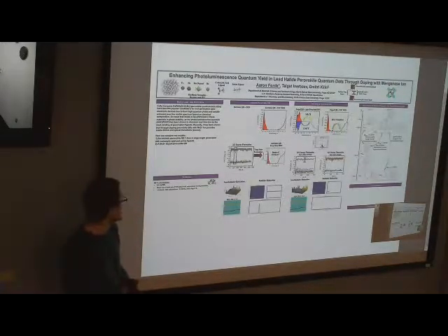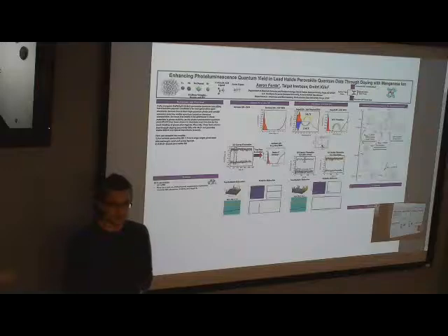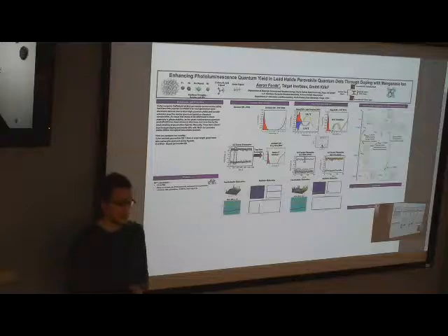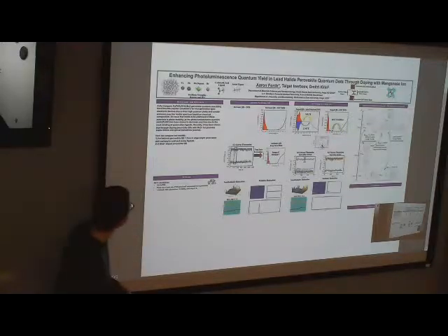And then we did molecular dynamics at 300 degrees Kelvin with a thermostat attached. We did that for about 1,000 ionic steps. And then for the excited state dynamics, we used Redfield theory for the non-radiative relaxations, and for radiative relaxations, we use oscillator strengths to get those.